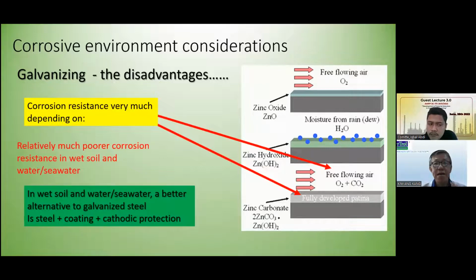Yeah. So this is, again, the environment will determine the performance of the material itself, not just the material. So it works very well in the atmospheric environment, but it performs very poorly when buried underground or submerged in water. So when it comes to wet soil and submerged in water or seawater, a better alternative to galvanized steel is using just a steel with coating, allowing a reasonable percentage of coating defects or holidays, plus cathodic protection. This will give a much better corrosion resistance performance as compared to hoping on the galvanized steel.